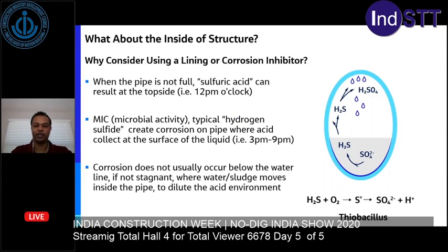So what about the inside of your structure? Well, you can consider using a lining or corrosion inhibitor. When your pipe is not full of product, you can have sulfuric acid occur at the top side of your pipe at the 12 o'clock position. At the 3 and 9 o'clock positions, as the picture depicts here, you can see where hydrogen sulfide might attack the pipe wall.